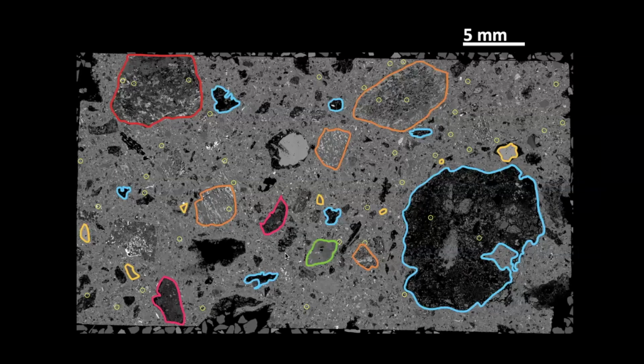So what I did was I took each of the thin sections and I mapped it in an electron microprobe to figure out really what's in it, the chemical composition. So this is a backscatter electron map, which is average atomic number contrast. A lot of the time, people talk about it as atomic number contrast, but the average is important when we're talking about polymorphs that have a density difference.